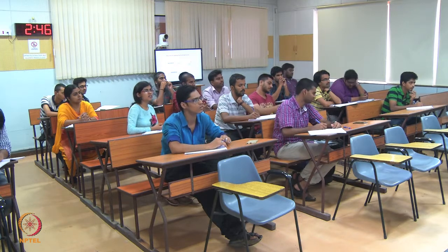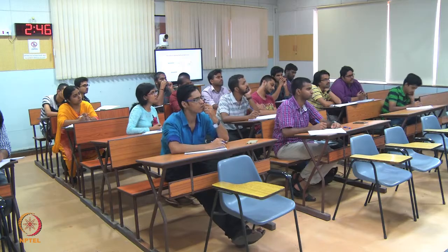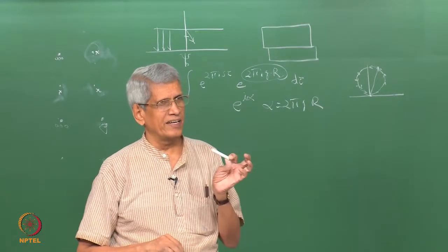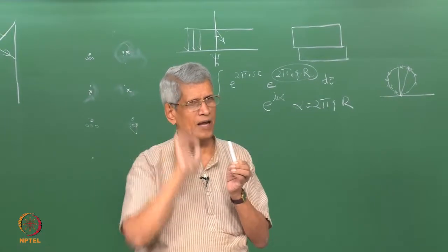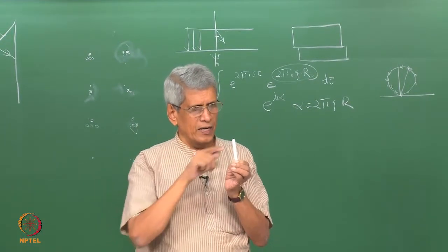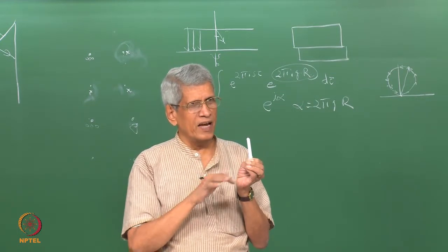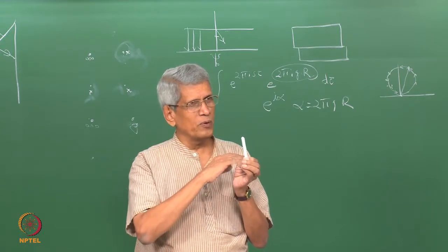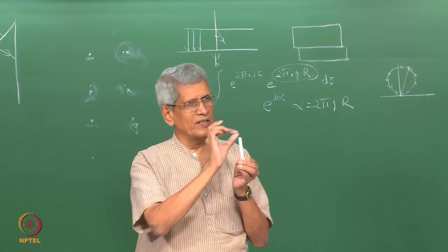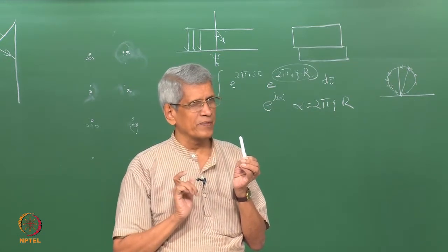That is, in an FCC, along the <111> direction, if we consider it, 3 layers A, B and C layers are kept on top of each other. Suppose I remove one layer. What essentially have I done? I have created a stacking fault, correct? So if that layer has been removed, now what has happened to that distance? What is the distance which we have made a modification? 1/3 of that distance, correct?